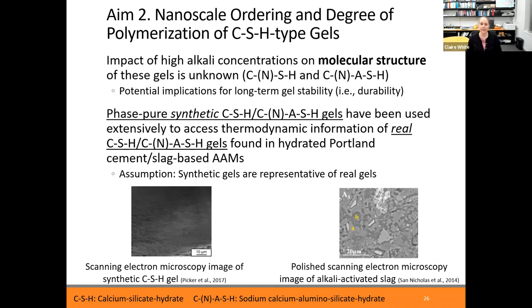So what we've done here is that we've made synthetic gels. So we can synthesize gels that are reminiscent of the real gels in real concrete. And we've synthesized them using different sodium contents and with and without aluminium. Now, there's one thing that people have assumed is that these synthetic gels are representative of the real gels that we find in the real concrete. And I'm going to discuss that today when it comes to one of the alkali activated concrete, whether this assumption is realistic. So that's one thing we're going to look at. And the other thing that we're going to look at just with the synthetic gels is the impact of sodium on the structure of the gel.